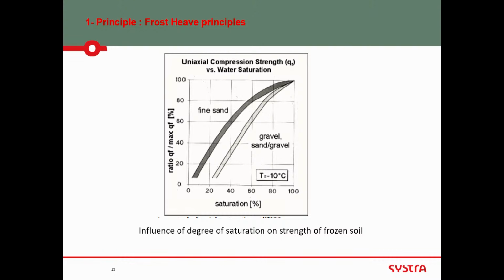And finally, what is interesting is to see the effect of saturation. As I said, all these figures that we have seen are for saturated material, where all voids are filled by water. The UCS, or the deviatoric stress, which is the same, so the q in the q diagram, the deviatoric stress is maximum when we get saturation of 100%, and if the soil is not fully saturated, in this case, the deviatoric stress at failure does not develop, because the sample has no UCS or very little UCS, unconfined compressive strength. Obviously, if you don't have any water in sand, there is no UCS. Okay. So these are the main bases of understanding that we have to have for a project.